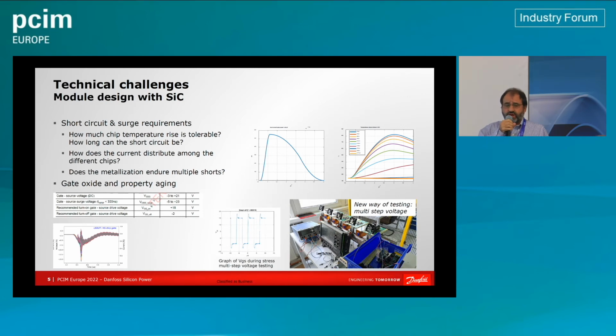A particular challenge with silicon carbide: the things that I told before are equally applicable for silicon and for silicon carbide. But in silicon carbide, we have a number of other things. One of them is short circuit and surge requirements. So here you can see on the left-hand side essentially a pulse during a short circuit. So this is a short period of time. And you see the temperature rise at each of the layers in the vertical stack of that module. And you can see that the top layers, the ones that are close to the junction, actually reach much higher temperatures. I can barely read this slide now, but it's about 800 or 900 degrees. And the lower layers, or the layers that are deep inside the substrate, are less affected by that.